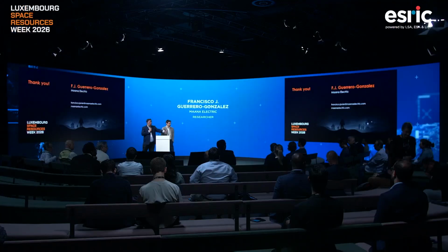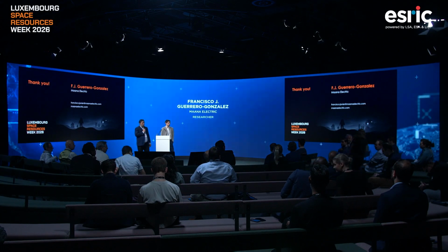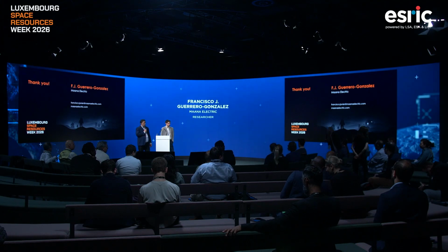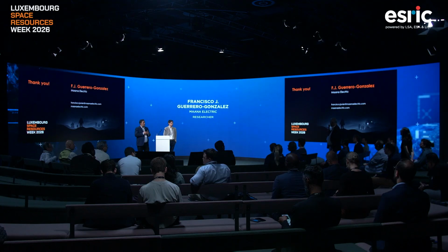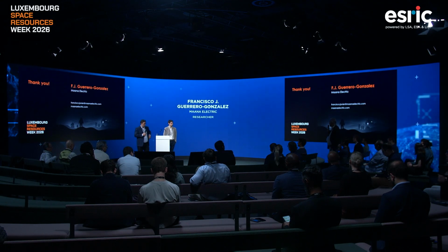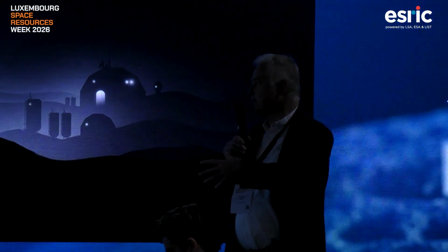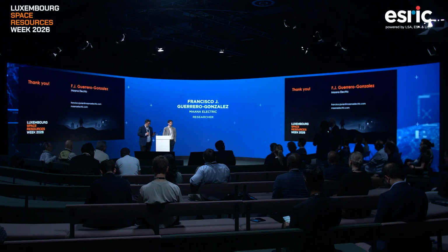The gentleman in the first row. Thank you very much for the presentation. Andreas Dietz from Fraunhofer IST. You mentioned that your electrolyte is molten calcium chloride, and the electrochemical potentials from the oxygen evolution and the chlorine evolution are very close together. That's a great problem in terrestrial chloralkaline electrolysis. Have you ever seen the chlorine evolution at the anode, and is it a real problem?